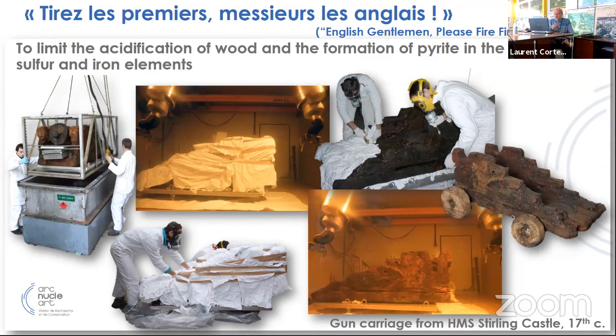So you can see here, on the left the handling in baths of acetone and then of resin, then the irradiation. We wrapped the wood with textile in order to absorb the excess of resin in surface. After the resin began to form a gel, we stop the irradiation and we control and clean again the surface if necessary before the complete polymerization of the resin.